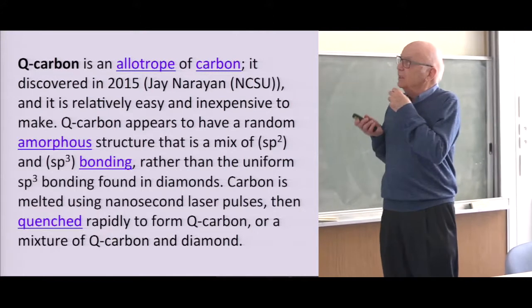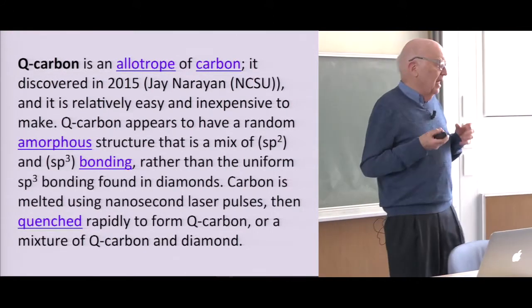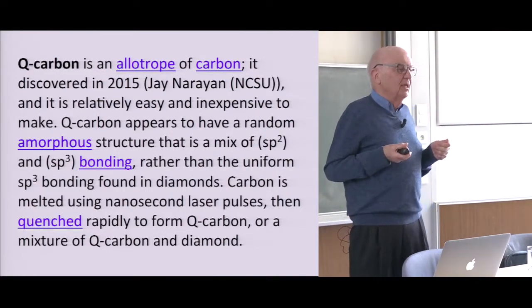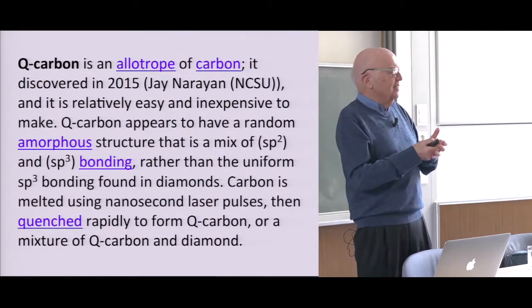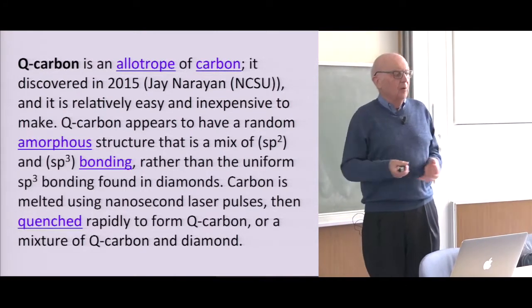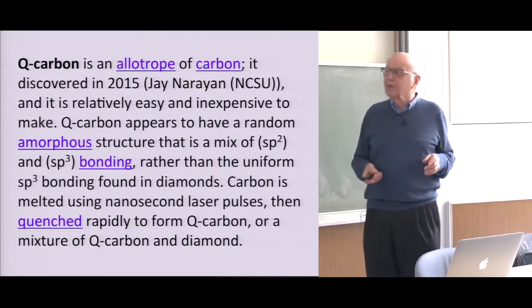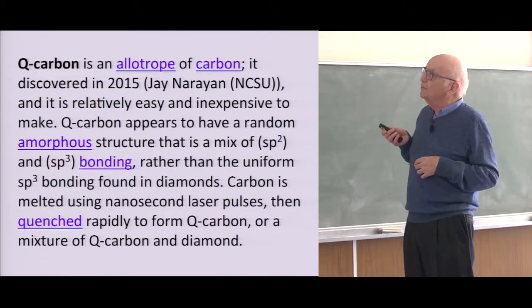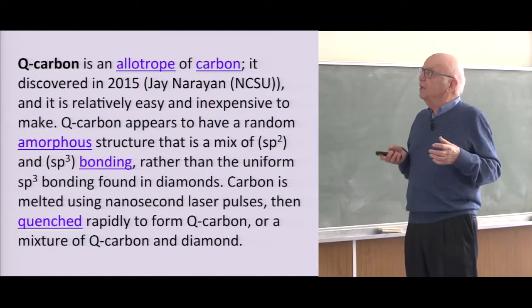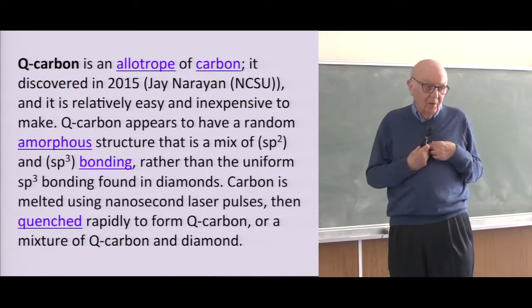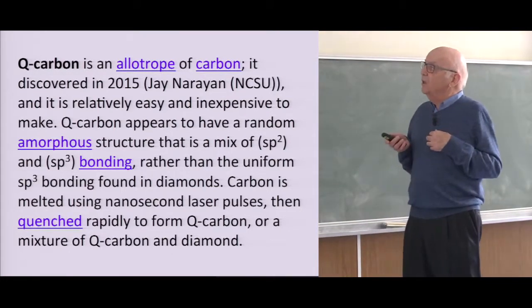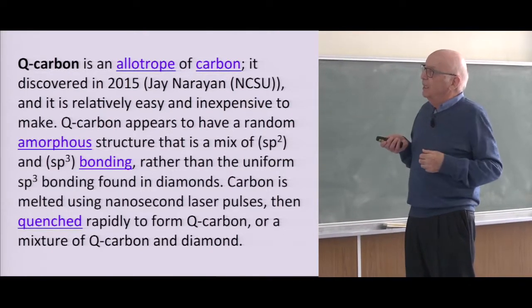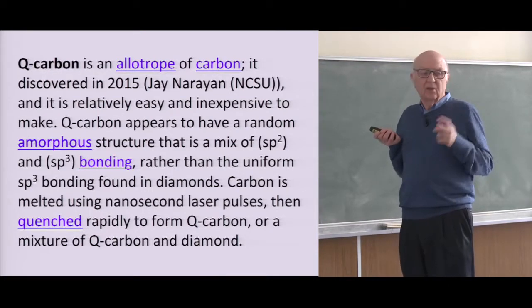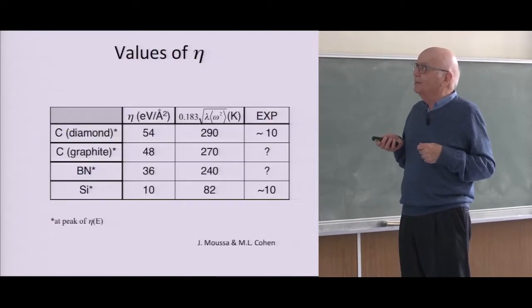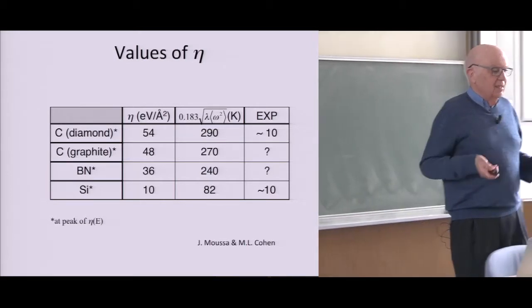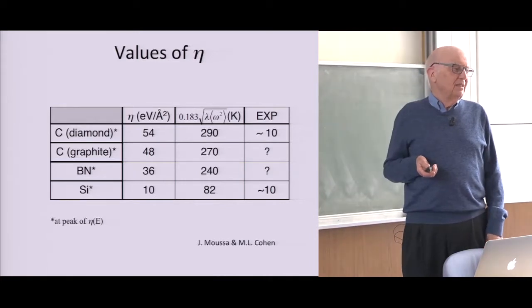So Q carbon was discovered by Narayan, and they make it by using high energy lasers, and I'm sure you have them here. And according to Wikipedia, it's easy to make. You get the carbon into a molten form, and then you quench it very quickly. Now, it's clear I'm not an experimentalist, and so when I say it's easy, I only go by what they told me. And it seems to be amorphous, and it has a random structure with a mixture of sp2 and sp3 bonds. All I care about is how much boron they got in. And so in this particular phase, I had made some calculations and felt that they could get more boron in, and they have. And so now they have quite a bit of boron in. Now, I just got an email here that they're up to 57 percent.